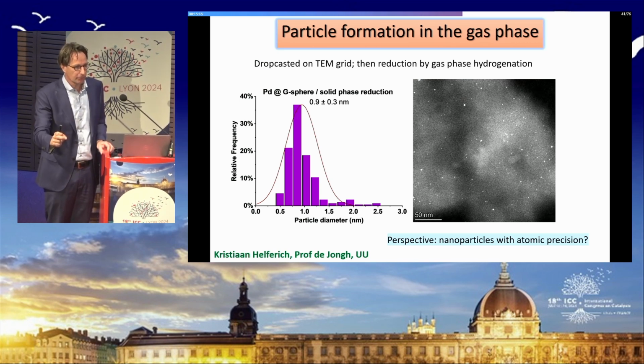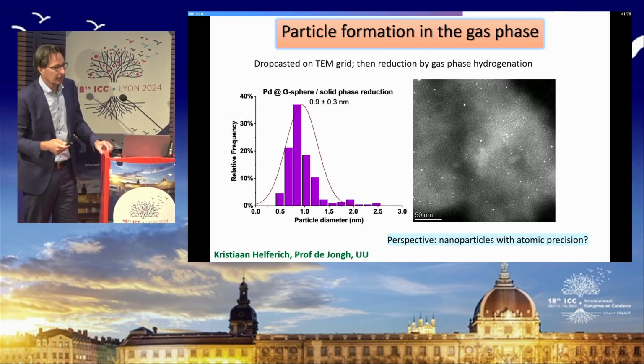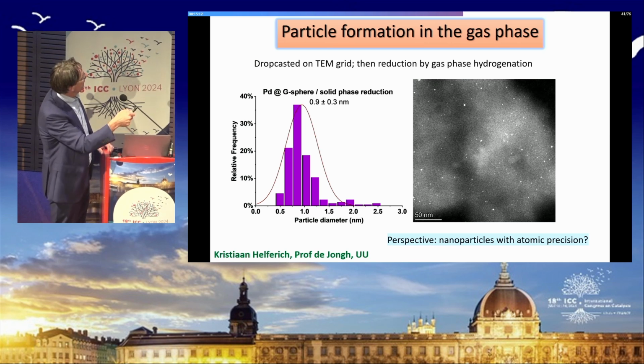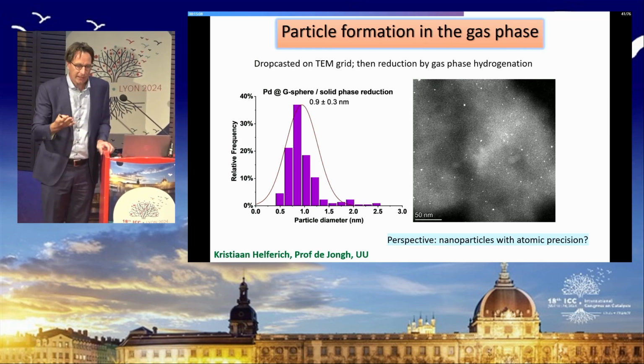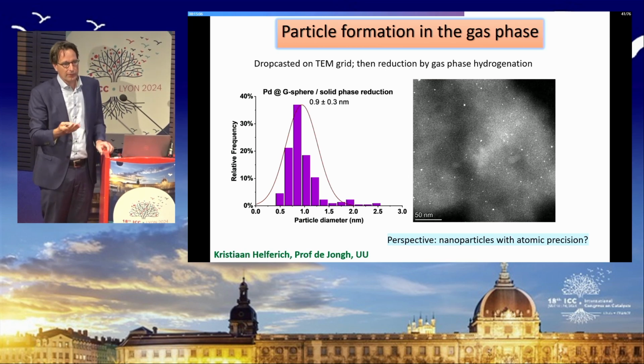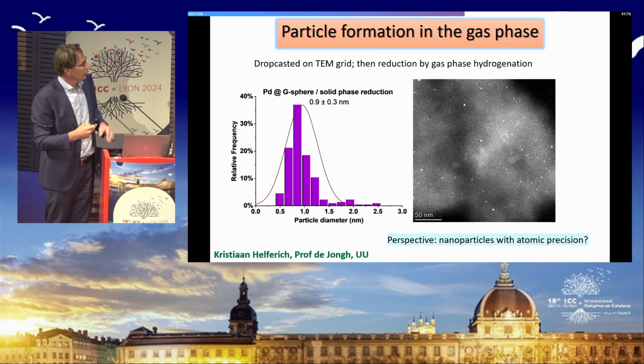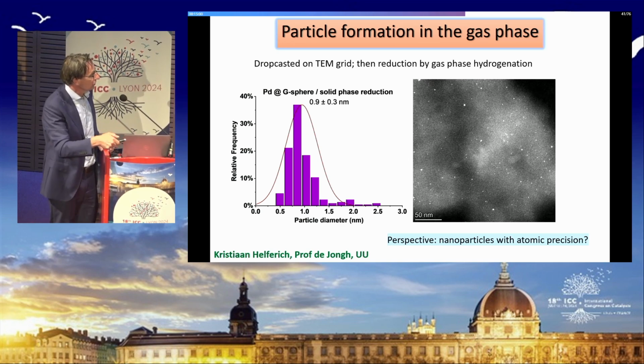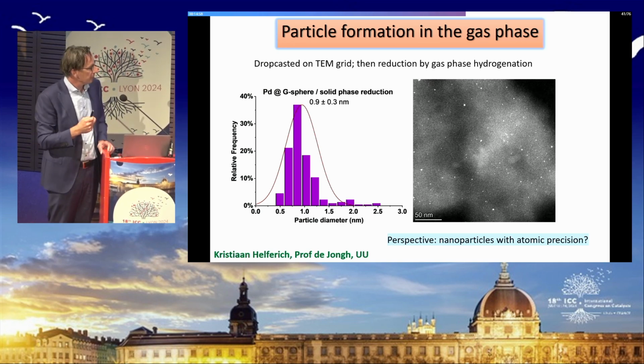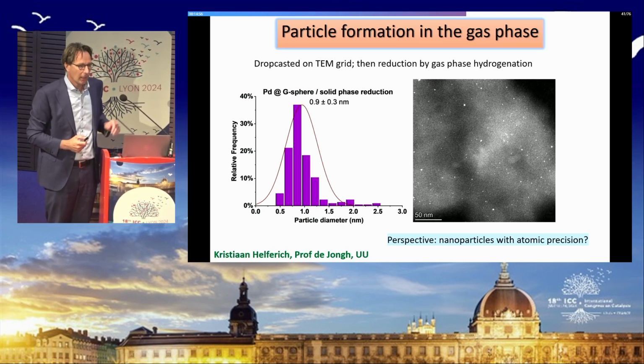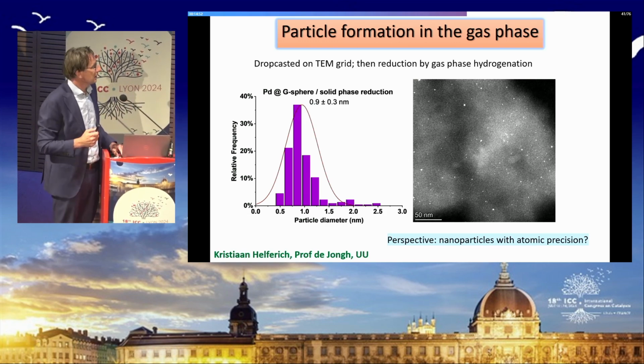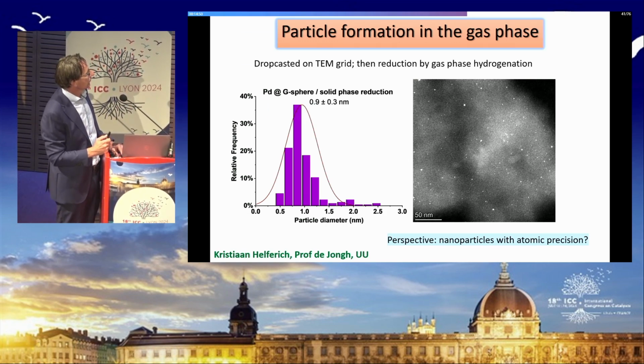reduction doesn't allow metal complexes to change from one cage to the other during the reduction time, we expected much smaller nanoparticles, and this is indeed what we observe. Nanoparticles of about 0.9 in line with what you would expect if you have about 24 atoms. So I think this is our lead, our perspective to nanoparticles with atomic precision, but we need to do a lot more experiments in this area to make this sound.